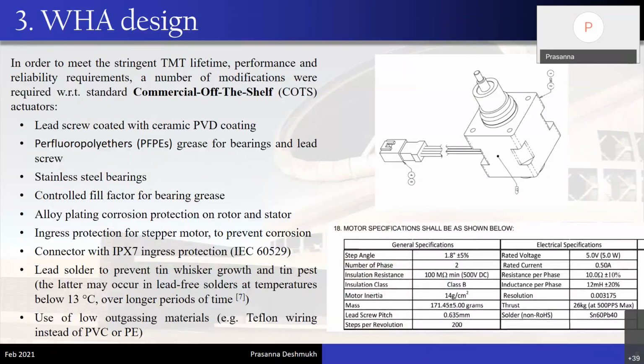Before we went ahead with selecting or designing a new actuator altogether, we checked the commercial off-the-shelf actuators available in the market, and we did find a couple of solutions, but they were not meeting the reliability requirements in terms of 50 years of lifetime. The reason was that many of them did not have the required protection against corrosion, which is an important parameter when you are using an actuator for such a long duration. We also required it to be waterproof, so that water should not enter inside, and it should have sufficient strength at its lead screw to withstand repeated operation, so that wear and tear doesn't happen. So all the possible options were not suitable for this, and we did select one off-the-shelf actuator and